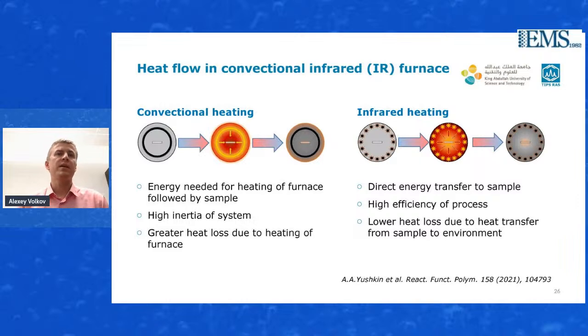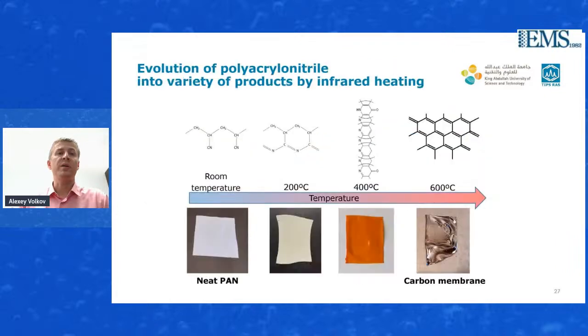And the difference between the conventional heating and infrared heating is that in the case of conventional heating, we have the heaters that transfer the heat from the walls of the oven to the center where the sample is located. But in the case of the infrared, it's vice versa. Infrared radiation firstly heats the sample, and then the heat transfer goes from the center to the environment. And that means that we can concentrate the heating on the sample, which might also reduce the time required for the transformation of the PAN material.